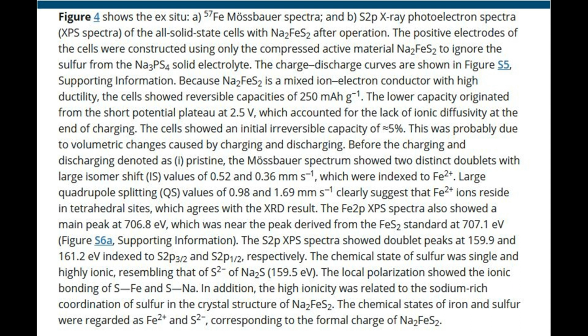The Fe2p XPS spectra also showed a main peak at 706.8 eV, which was near the peak derived from the FeS2 standard at 707.1 eV, figure S6a, supporting information. The S2p XPS spectra showed doublet peaks at 159.9 and 161.2 eV indexed to S2p3/2 and S2p1/2, respectively. The chemical state of sulfur was single and highly ionic, resembling that of S2- of Na2S, 159.5 eV. The local polarization showed the ionic bonding of S-Fe and S-Na.